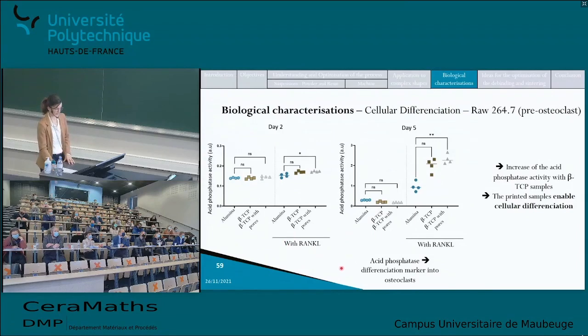And it appears that after 2 days, there is a slight increase in the acid phosphatase activity for the β-TCP with pore sample, and the same result is visible after 5 days. Even if here the difference is non-significant, it appears that there is a tendency that the acid phosphatase activity will increase with the β-TCP samples. So this means that the β-TCP sample enables the cellular differentiation better than the alumina sample.